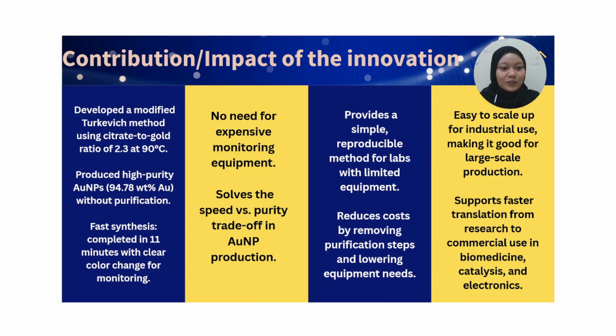Assalamualaikum. Now moving on to the contribution and the impact of this innovation. We have developed a one-step method to produce 94.78% pure gold nanoparticles using a modified Turkevich method with a citrate to gold ratio of 2.3 at 90 degrees Celsius, and it requires no purification.